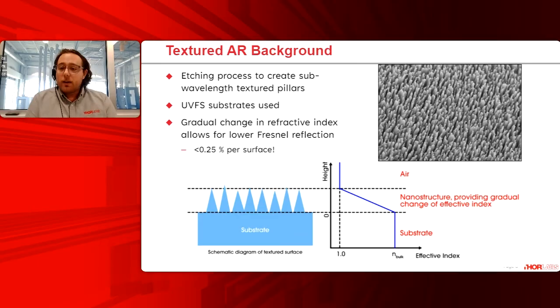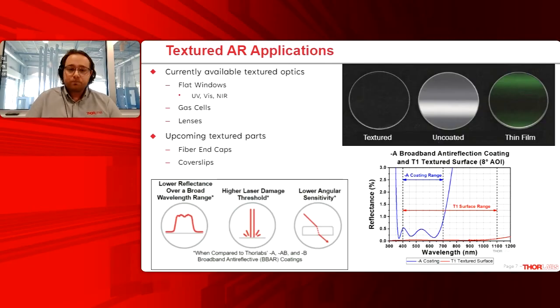Currently, we fabricate these in UV fused silica glass, and we use an etching process to create sub-wavelength textured pillars. Now, these sub-wavelength pillars allow for a gradual change in refractive index, as opposed to the abrupt change in standard optical substrates. This gradual change can reduce Fresnel reflections down to less than 0.25% per surface, and this is over a much larger bandwidth as well.